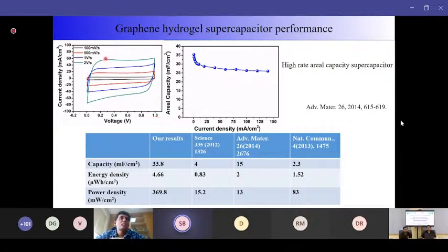But what happens is, because I have used graphene, above a certain voltage graphene can also catalyze and give rise to some oxygen evolution or hydrogen evolution. So to be on the safer side, we chose up to 1 volt, not 1.23 volt. 1.23 volt is the theoretical limit. We kept below that because you have to check the catalytic activity also. Whether on reaching 1.23 volt we are getting some huge increase of current here or here. If we are getting a huge increase of current, that is not due to storage of the ions, that is basically due to catalytic activity. Now, if you want to go beyond 1 volt, to like 2 volt or 3 volt, you have to use other electrolytes, not aqueous-based electrolytes.